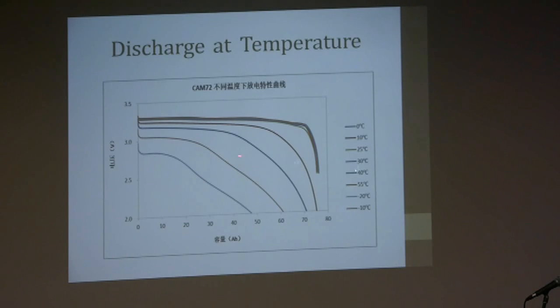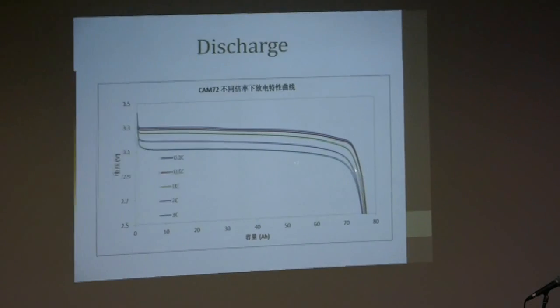So you see that the fact that these curves are so far away from the proper ones will already tell you that the battery is actually not happy here. It's not working the way it's supposed to work, and that's just because of the temperature. So if you charge them quickly at these temperatures, you damage them.